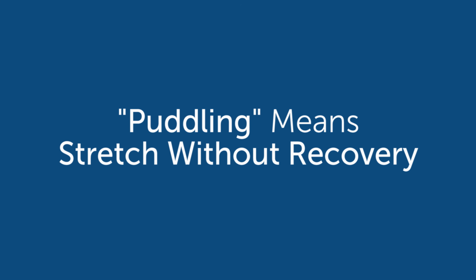One thing I've heard often used is puddling. Not like water. What do you mean by puddling? Puddling is not good, obviously something you don't want. It's like a long continuous booth. When people are sitting on it, all of a sudden you start to see a little ocean effect where the material is not recovering. Usually that's caused because a low density foam is being used, or they're using a substrate on the product itself that is stretching but not recovering itself.